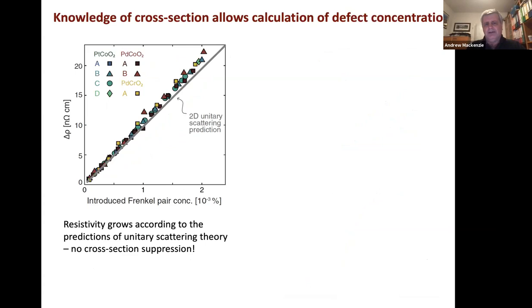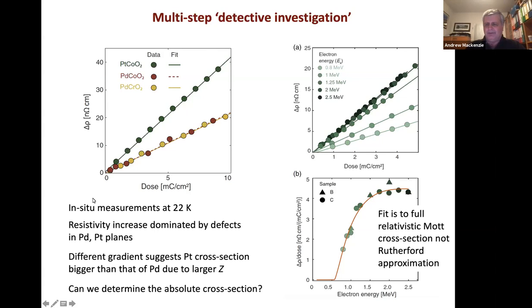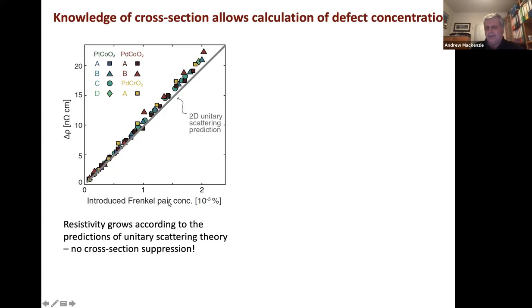So once you've done that, you're no longer talking about dose on the axis at the bottom. You're talking about induced Frenkel pair concentration, and this is in 10 to the minus 3%, right? So that's in parts per 100,000. And you see that the resistivity rises, and these are three different compounds, many different crystals. The resistivity rises always at the same rate once you've converted properly with the cross-section to get the defect density.